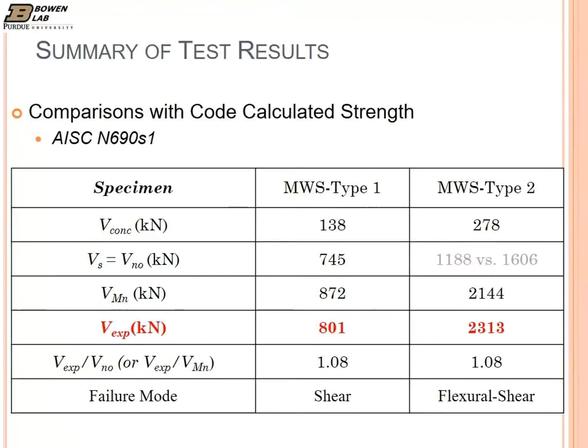And now let's look at the numbers back again. I already mentioned some of these. The first specimen failed in shear. That was the experimental strength. When we compare with the code calculated equation for this specimen, the steel strength governs, and we have an 8% safety margin when we compare the strength. And you see the flexural strength for the type 1 specimen. It didn't get there because it failed in shear, therefore it went into flexural yielding. But a different story for the type 2 specimen. We had experimental strength. This time comparing with the flexural design strength, we see an 8% margin, and it failed in flexural shear because both things happened simultaneously. That's what we call this type of failure.